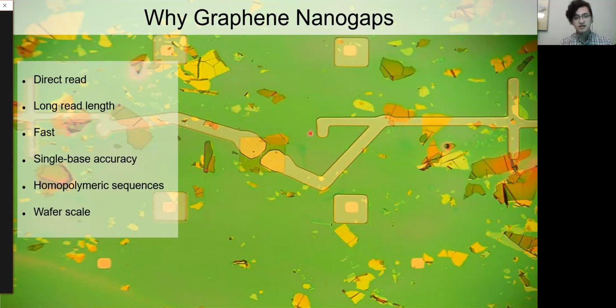As you can see here, EBL, or electron beam lithography, was used to etch a resist onto our wafer, where we will deposit gold to make gold electrodes leading to the graphene, and we will position a graphene flake right over those electrodes.